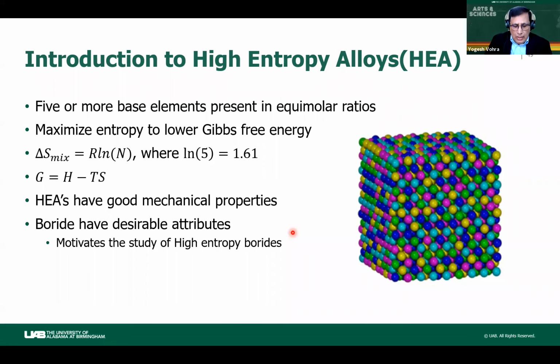Okay, so in the last part of my talk, I'm going to cover something new which we have started looking at, are these high entropy materials. And this is a very exciting area in material science. Think about a high entropy material as one where you have more than 5 elements which are distributed randomly in a crystal structure. So it could be a high entropy alloy, it could be a high entropy oxide, it could be a high entropy carbide, it could be a high entropy boride. The idea here is that the metallic elements are 5 or larger and they are distributed randomly.